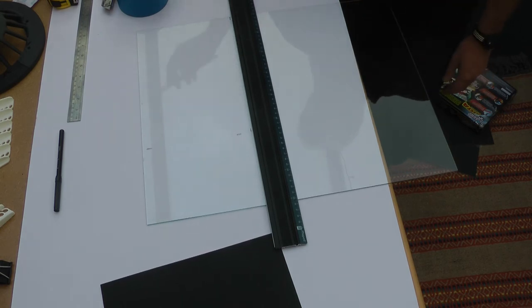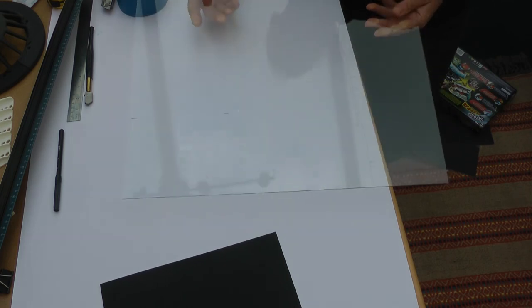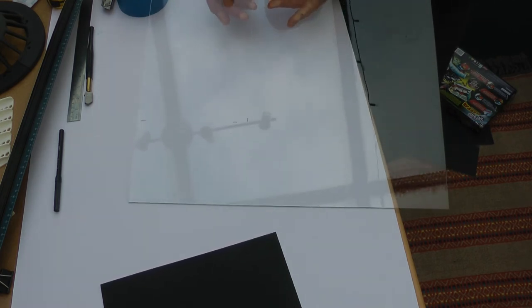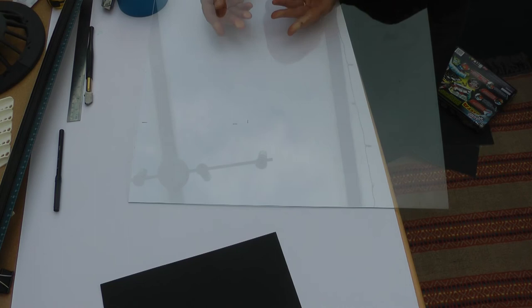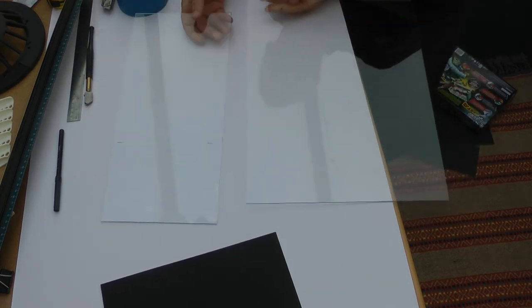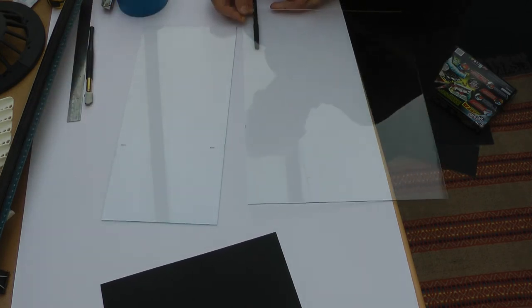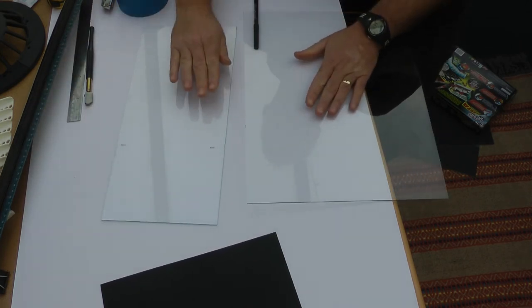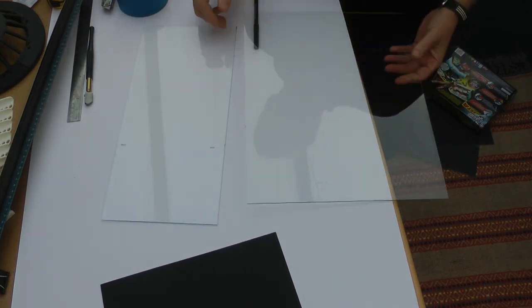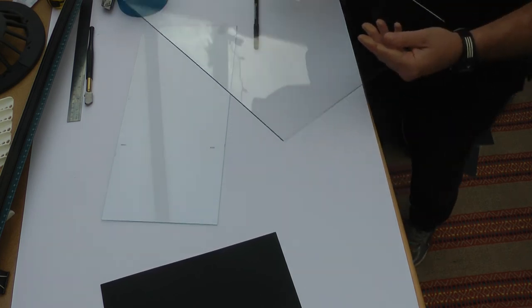So you don't need to do any more with that. That's what you're looking for. And as you can see, there's just a slight scribe mark on the glass. And to actually break it, all you need to do is literally just hold the plate. Just take care because it is glass and it is sharp. And then just pull it down. Just push the two edges up and it'll break really cleanly. Another way of doing it is to put perhaps a pen or a mat underneath it and just hold it there and press down the side. But I just normally do it that way and it works great.